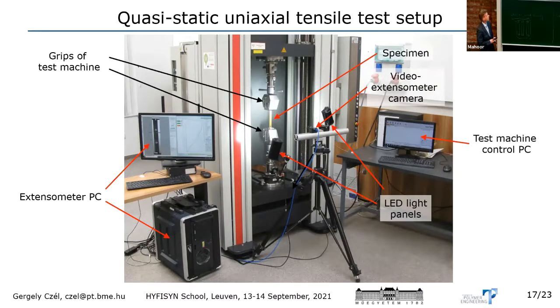And as I mentioned, we don't have end tabs. We just clip the specimen, and we tend to use sandpaper at the end of the specimens because we have mechanical wedge grips, which have quite sharp and quite deep nails. So it would penetrate in the specimen quite deep, maybe enough to compromise the strength of the glass layers, the protective layers. But just using the sandpaper, it distributes this aggressive effect, and it stops these nails penetrating too deep in the specimen surface at the grips.